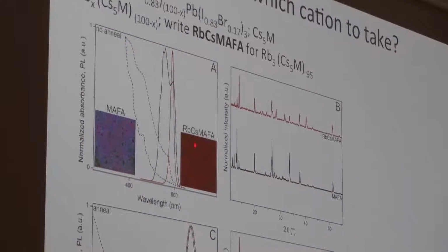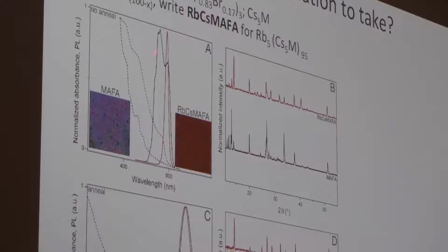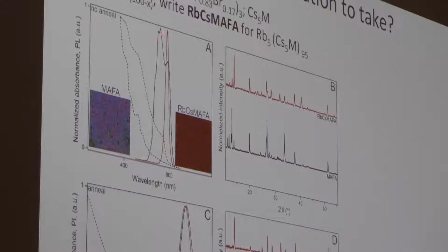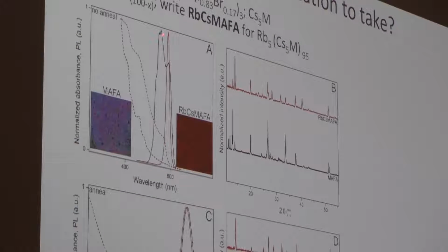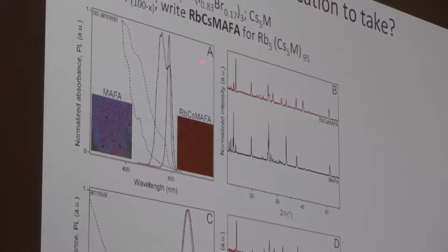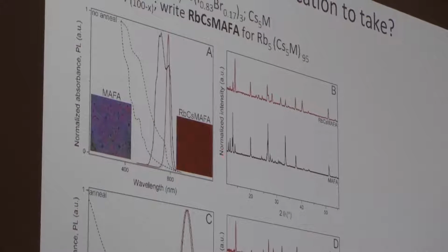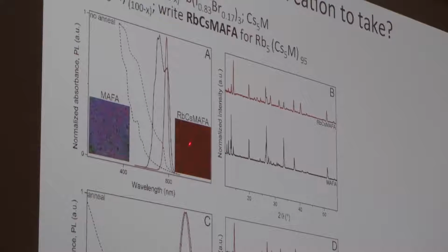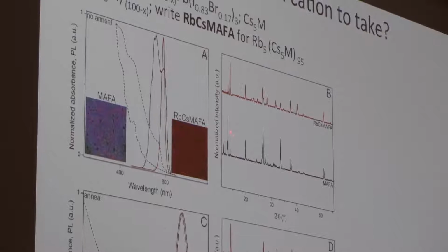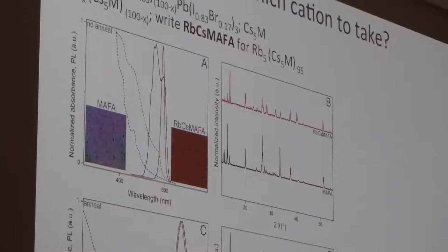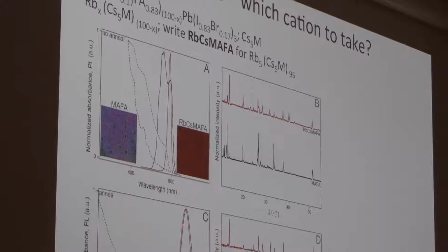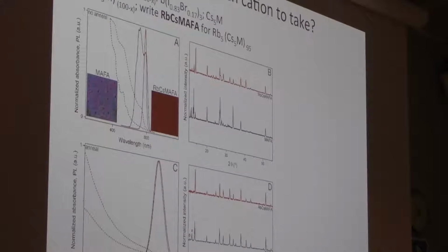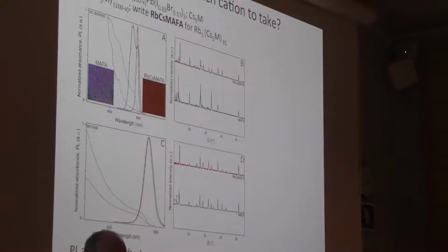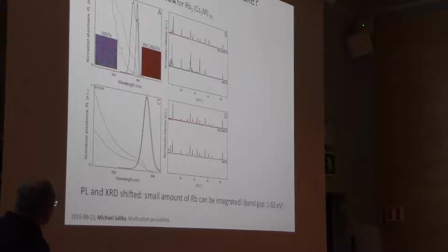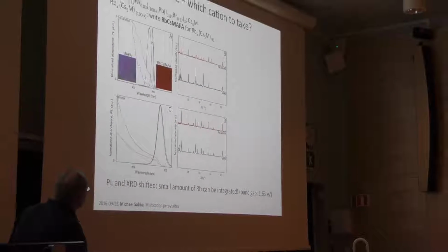But you also see here, this is if we have the MAFA compared to the quadruple here, this is the fluorescence. You see it's before annealing. So we have here formation of not complete perovskites. There is some emission which is broad. We have some impurities from the XRD. If we have this mixing, we have a nice sharp fluorescence peak, and we have removed some of the impurities. If we anneal at 100 degrees, you see the fluorescence peak overlap completely. So with the mixing, we do form perovskite structure at room temperature, we think, at higher quality. So that's what we think is happening with the perovskite formation.